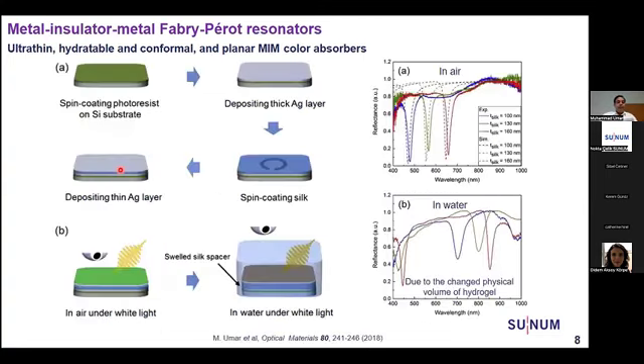For that, in our work, in this case we use a photoresist. I will discuss next why we use it, but we sandwich a hydratable silk biopolymer between two silver films. In air, this is the resonance spectrum of the devices fabricated with different thicknesses of the insulator layer. If we increase the thickness of the insulator layer, we can tune the resonance spectrum. So we fabricated blue, green, and red color absorbers by fixing a thick silver bottom layer.